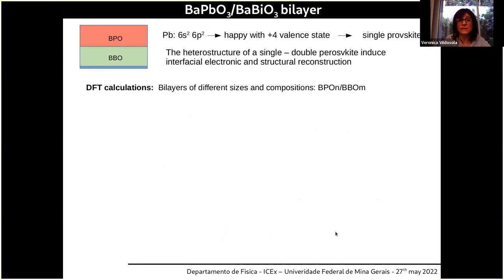So we decided to study this heterostructure, BBO and BPO, from first principles. Just a brief comment about what this BPO material is. Lead has, instead of 5 electrons as bismuth, 4 electrons. So this lead material is very happy with the +4 valence in this combination of perovskites. So it grows in a single perovskite crystal structure. And the heterostructure of a single and a double perovskite induces interfacial electronic and structural reconstruction.